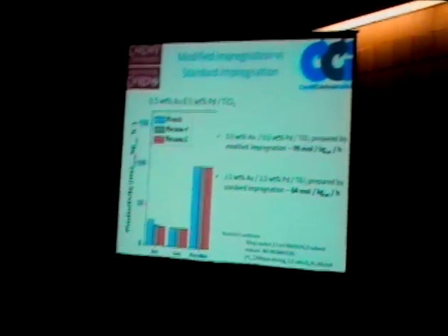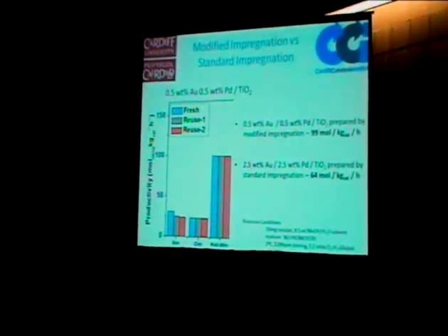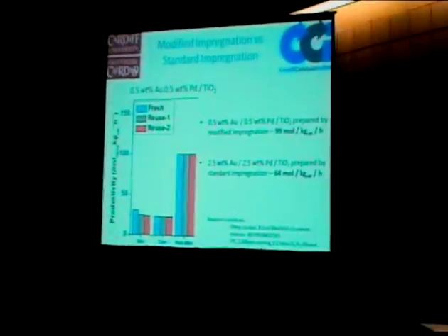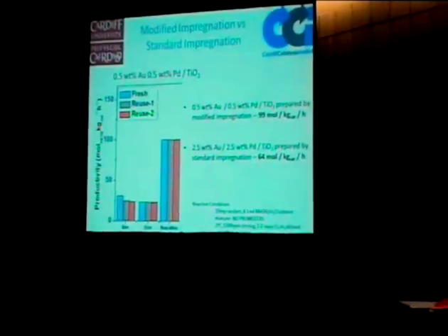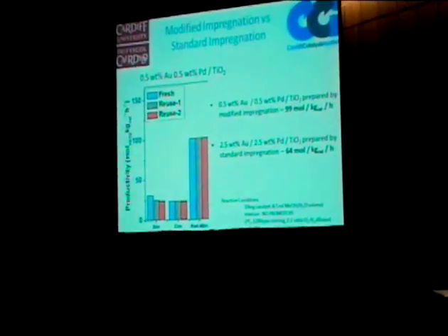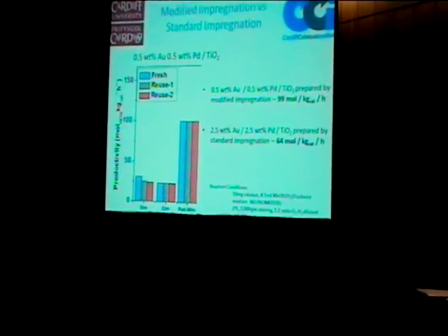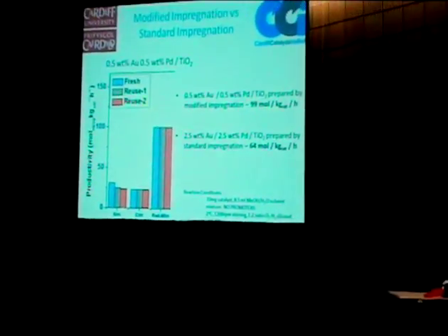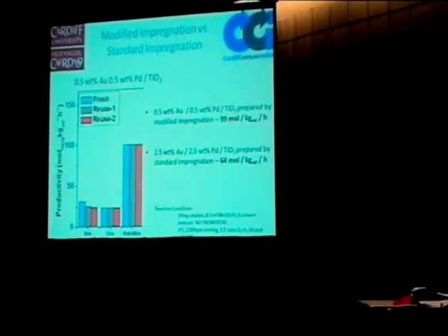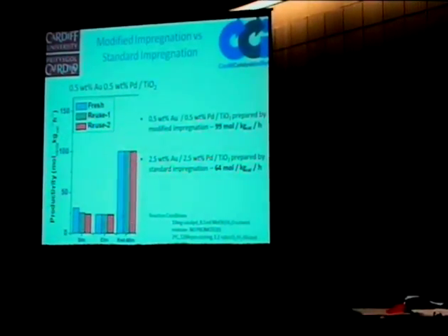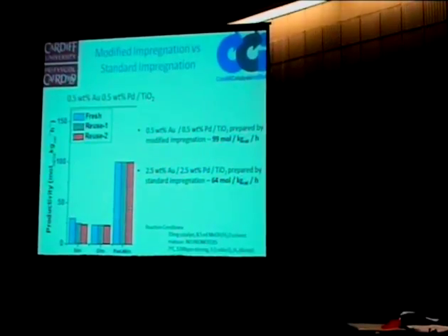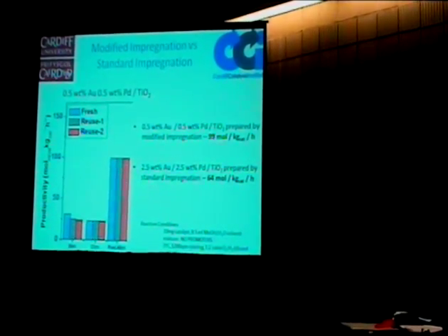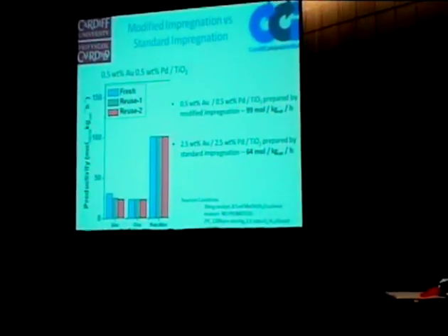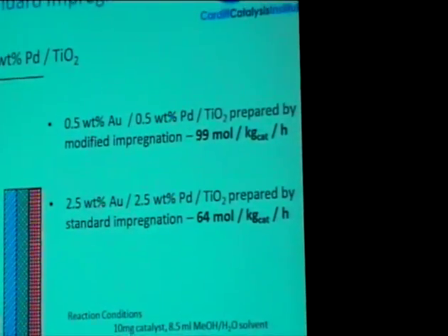So as you can see, we get a big increase in our hydrogen peroxide synthesis activity. So if we compare this low-loaded catalyst to our typical 5 weight percent catalyst, we can see it's even better than our 5 weight percent catalyst. It means we're using the gold and the palladium much more effectively in this preparation method. These catalysts are also stable to multiple reaction cycles in the autoclave.